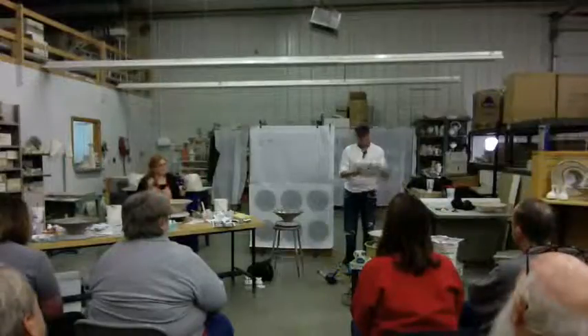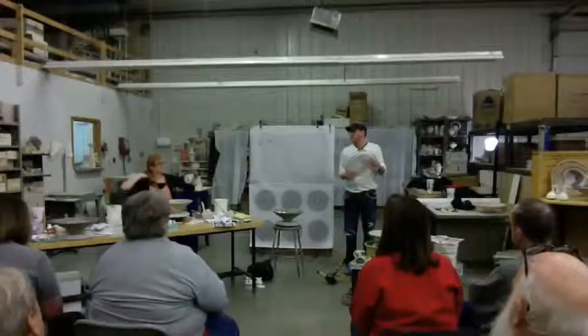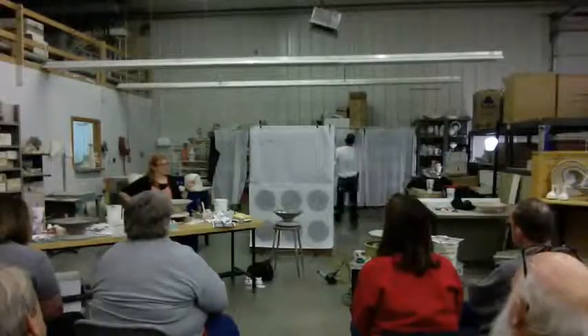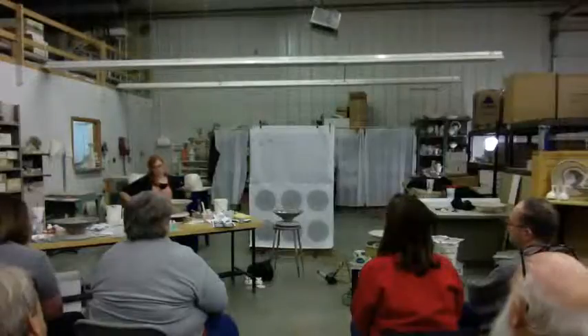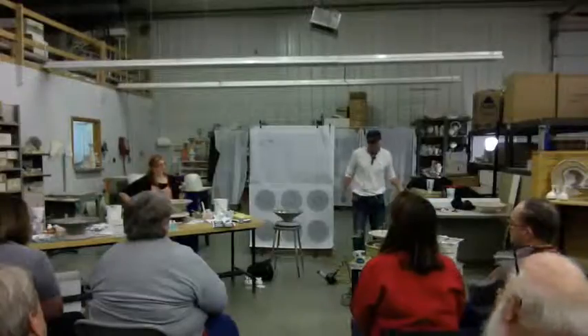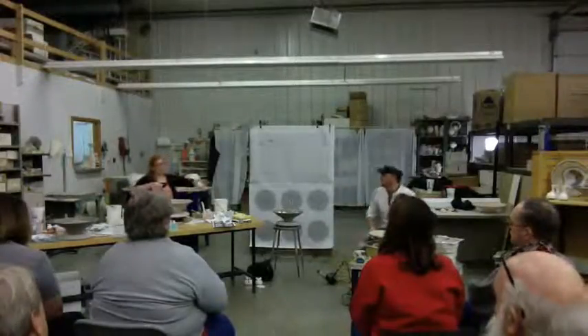I had no regrets ever switching over to the Hydrobat. It's a combination plaster and hydrocal, so they're actually stronger than a plaster bat and a little more lightweight than some of them. And so I started throwing plates on them and basically stopped having any of the issues that I would ever have with plates, like cracking or the unevenness because of the wire.